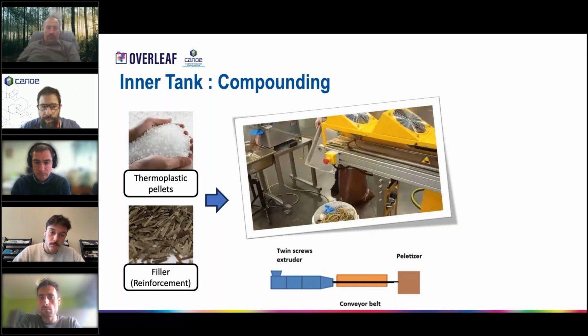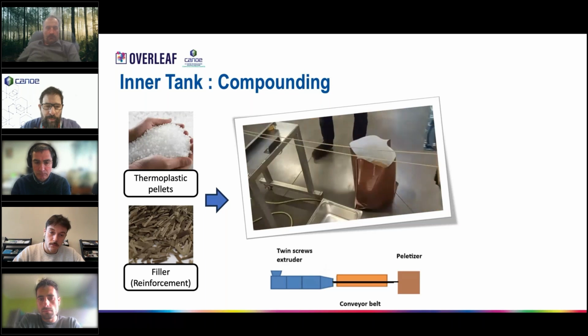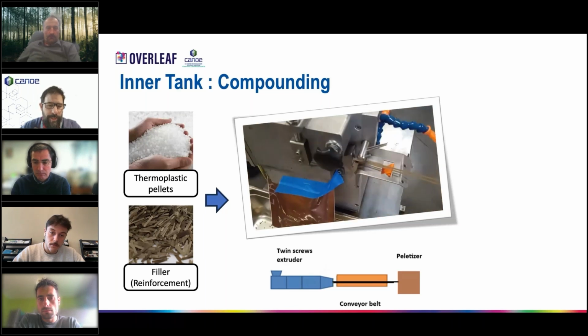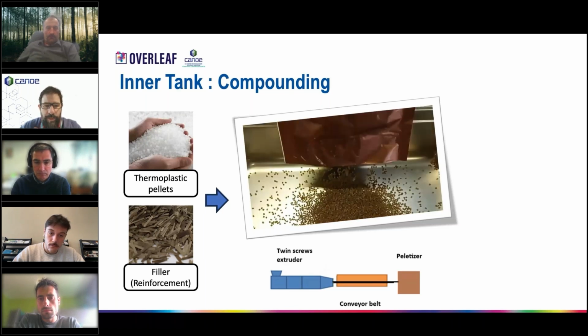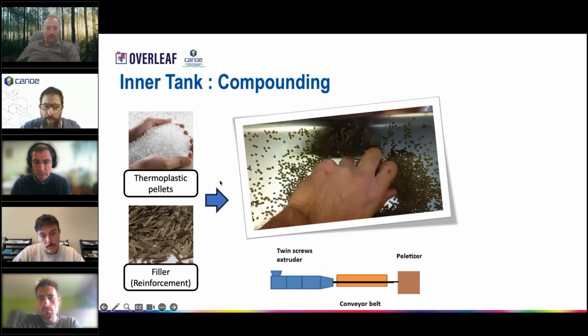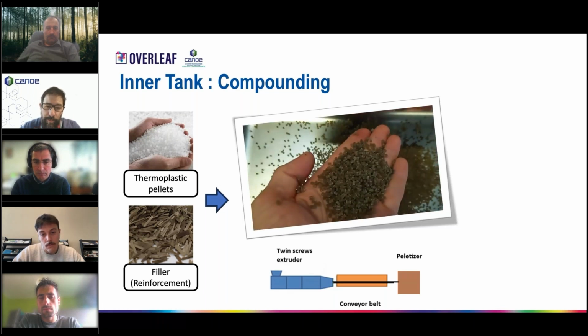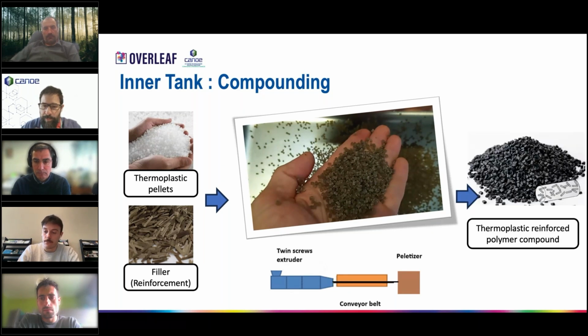And then you can see the cooling process, and then the pelletizing process in order to produce pellets. Obviously, in these pellets, the fibers no longer have 6-8 millimeter length. It's a bit shorter because of the grinding and the shearing of the screws. But anyway, the fibers still have something like 0.5 to 1 millimeter length inside the polymer itself. You can see a schematic representation of this in the picture here.